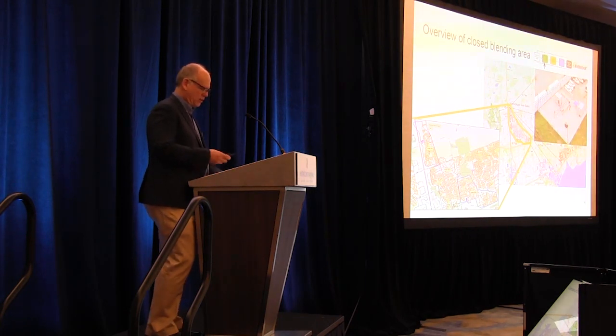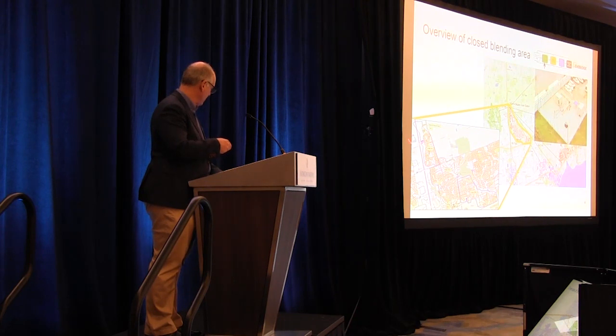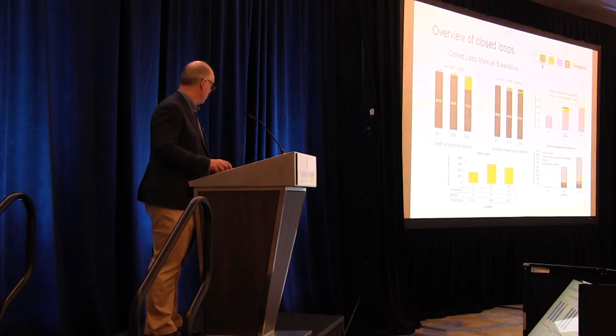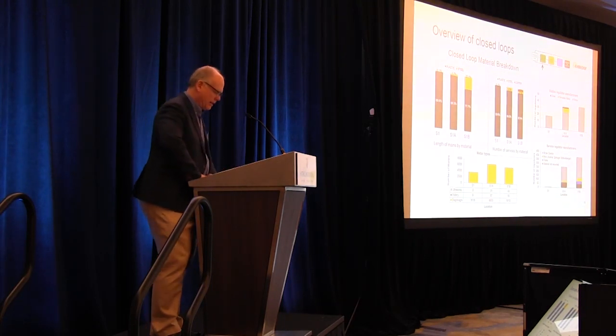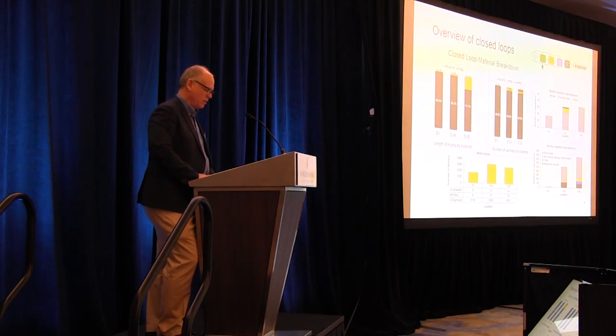One of the things that we wanted to look at, though, was not only the close proximity, but also some of the other material characteristics, which I'm going to talk about a little bit more here, just comparing those 3 subloops. So just some material breakdown. The loop S1, the one that we actually picked, is almost entirely plastic pipe. It's got a little bit of steel pipe in it. So it's very homogeneous, which is an advantage because it cuts down on the number of different materials you're looking at. The services within that, we basically have 3 types of services: plastic, steel, and copper. And almost entirely, that S1 is all plastic services.